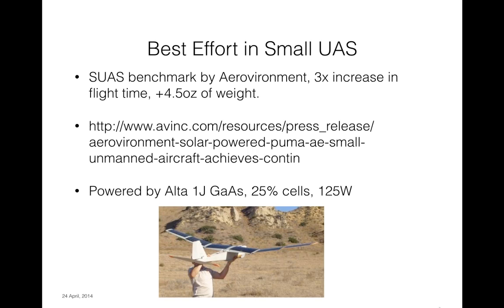The way this was built is they wet the mold out with epoxy, and then they lay the solar arrays in there. They're just like paper, very thin, 100 micron thick solar film of interconnected sheets of cells. They lay that in the mold, put the fibers and do the rest of the layup on top of that, clamp it shut, cure it, and pop it out of the mold, and you get this fully integrated bonded solar panel without adding any additional adhesives or laminating films to protect the solar film. So we added literally 4.5 ounces of weight and put 125 watts of power available on that aircraft.